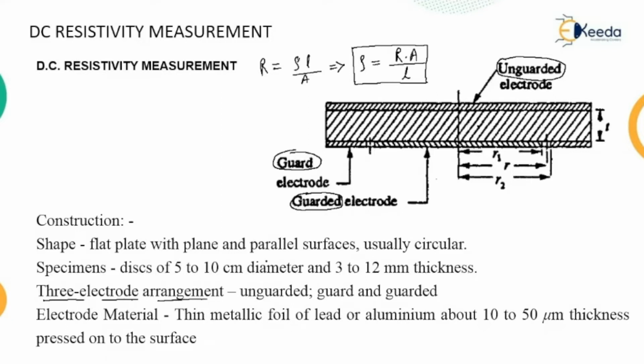The electrode which completely covers the surface of the specimen is called the unguarded electrode, and it must be connected to the high voltage terminal. The third electrode, which surrounds the other measuring electrode, is connected to a suitable terminal of the measuring circuit. The width of the guard electrode must be at least twice the thickness of the specimen, and the unguarded electrode must extend to the outer edge of the guard electrode. The gap between the guarded and guard electrodes should be as small as possible. You can see here the space between the guard and guarded electrodes is very small.